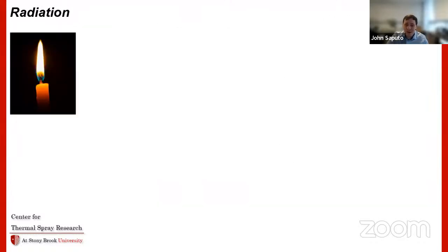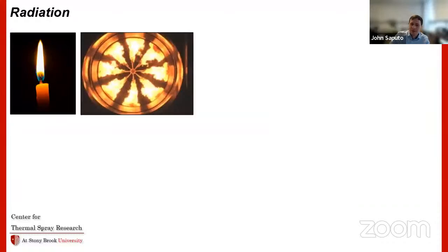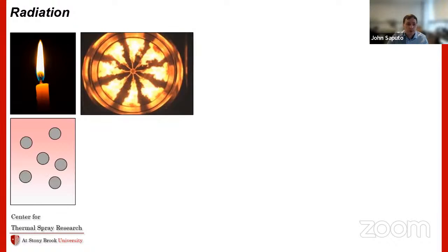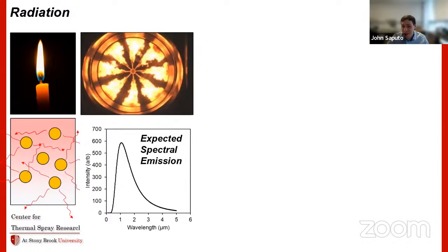A diesel engine is a whole lot like a candle. If you look at this optical engine test, you can see something in common here. You have a lot of radiative heat transfer that's emitted from these things. It comes from hot gases, your particulates, soot suspended in this sort of dirty diesel flame. As those soot particles get hot, they emit radiation kind of like a black body. So if you look at the spectral emissions that come out of these, there's a peak between about 1 and 2 microns, the expected maximum radiation, taking the adiabatic flame temperature of a stoichiometric mixture of diesel fuel and air.